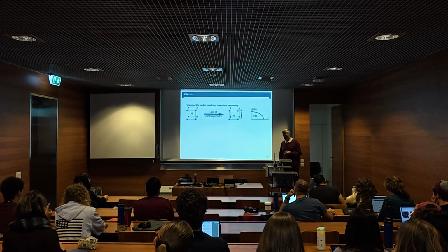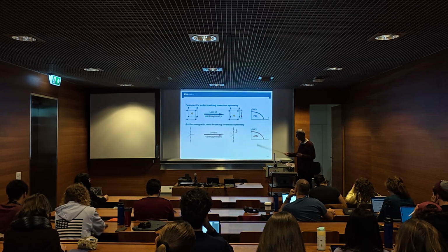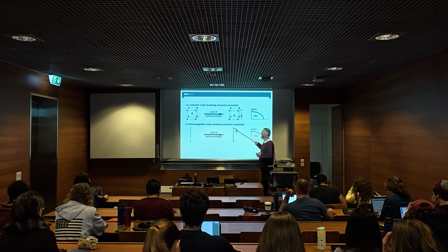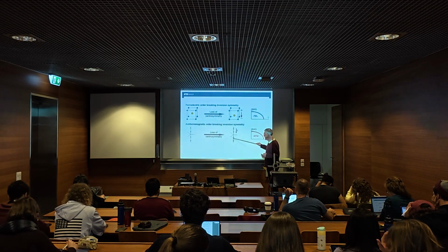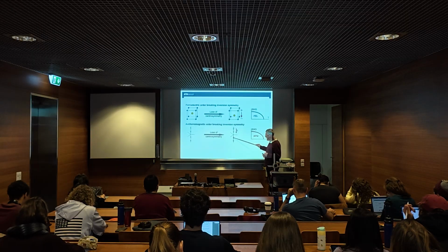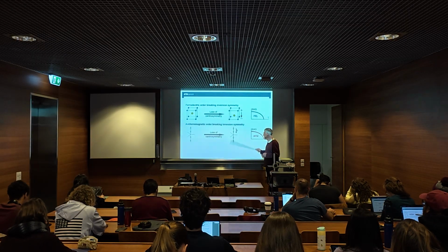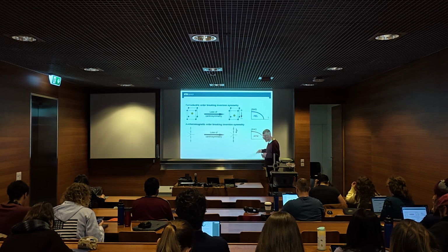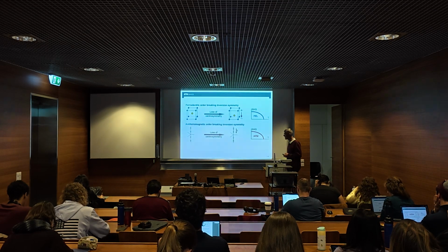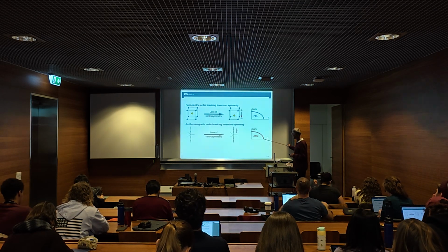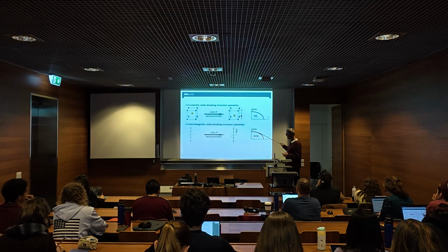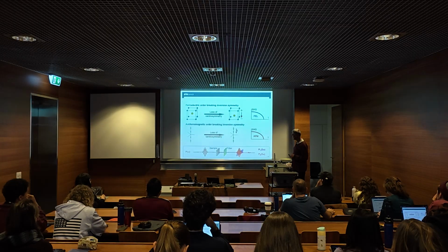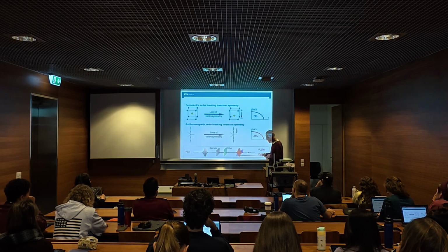And that does not only work for ferroelectric order, it can, for example, also work for antiferromagnetic order. So if you take our chromium oxide again, down, up sequence of spins, that breaks inversion symmetry. Inversion would move the down spins from that side to that side, where there is an up spin, so it violates inversion symmetry. Again, you get a frequency doubled signal background free from the onset of magnetic order.